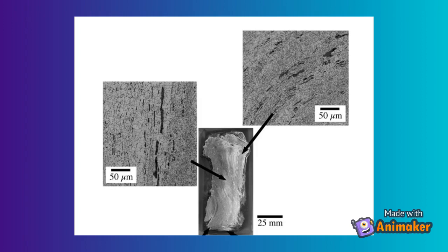The orientation of the microstructure within the wrought iron also greatly impacts the tensile strength. If the iron is in a parallel direction to the silicate slag within, then the tensile strength is considered high for the material. But in the case of the Titanic's rivets, analysis found the microstructure to be perpendicular, which negatively impacts the integrity of the iron. This creates a large amount of space within the material that is susceptible to fracture. Likely this is the case as to why many of the rivets were found to have been snapped or fractured in the wreckage of the Titanic.